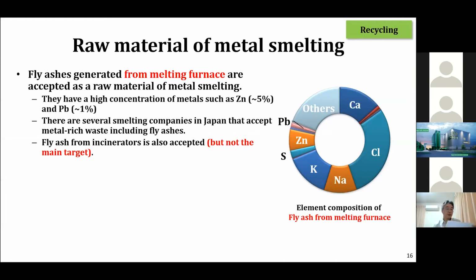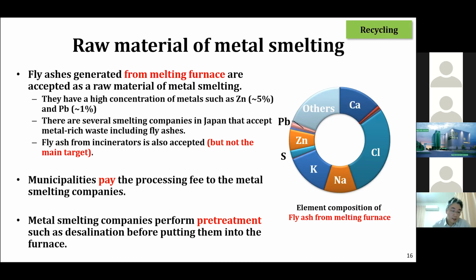I would like to introduce one more recycling technology, raw material of metal smelting, especially for fly ash generated from the melting furnace. The secondary fly ash has a high concentration of metals such as zinc and lead, and there are several smelting companies in Japan that can accept metal-rich waste, including fly ashes. As a result, part of fly ash from incinerators is also accepted, but not the main target. In this case, municipalities pay the processing fee to the metal smelting companies. And metal smelting companies need to perform pre-treatments such as desalination before putting them into the furnace.